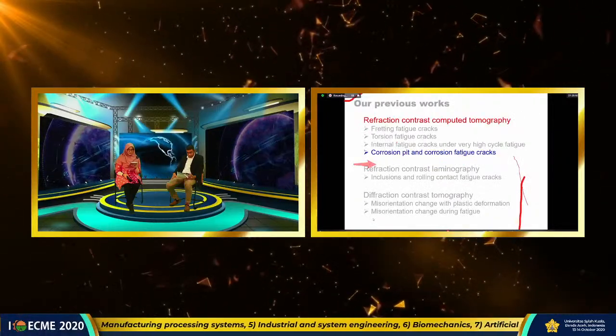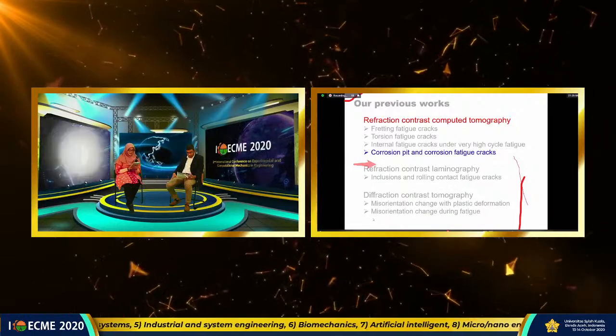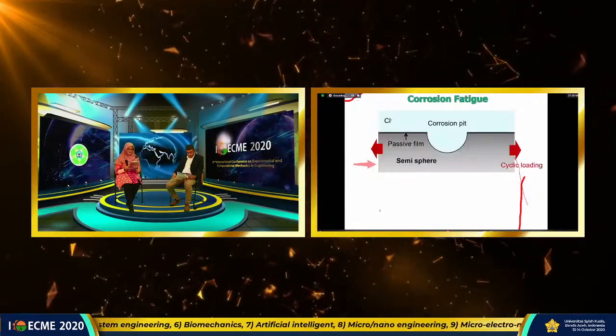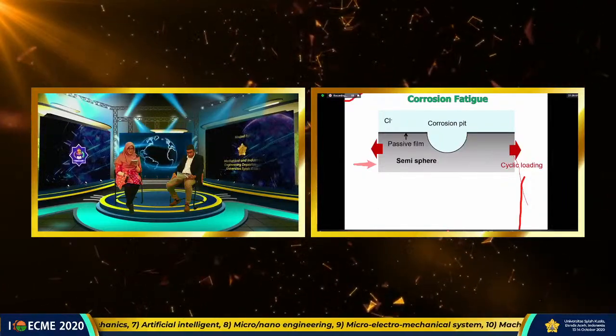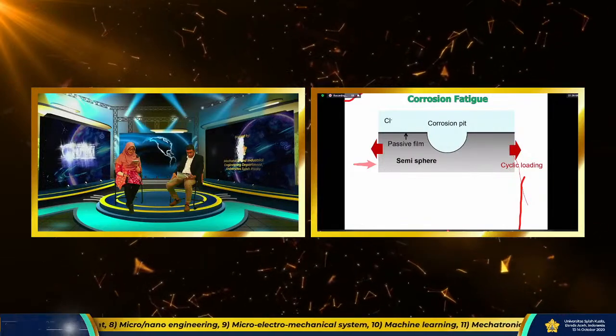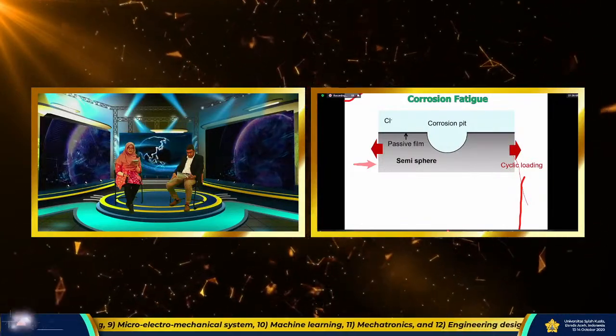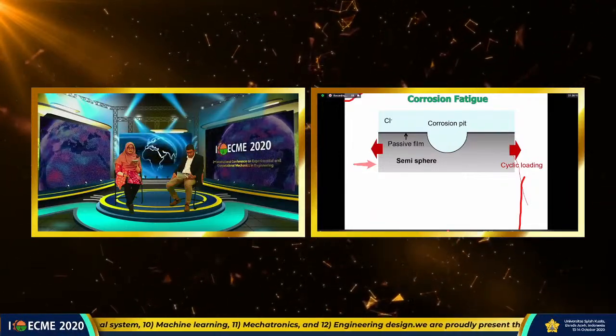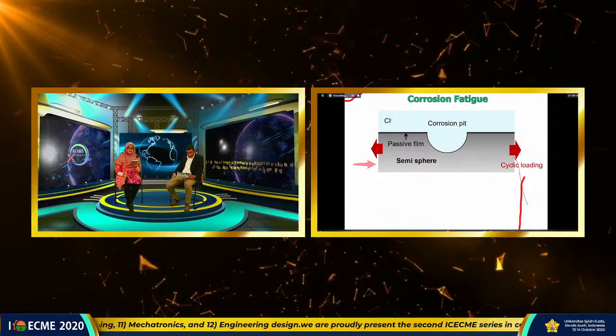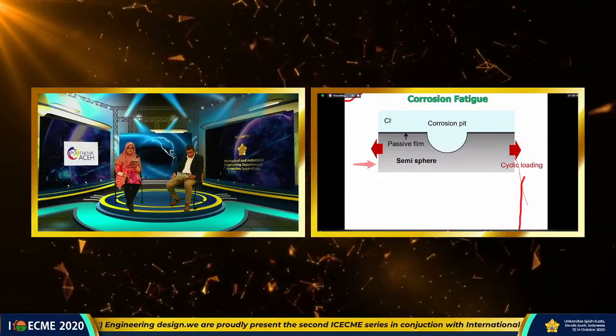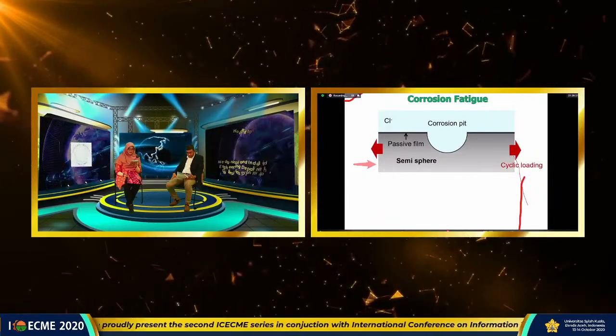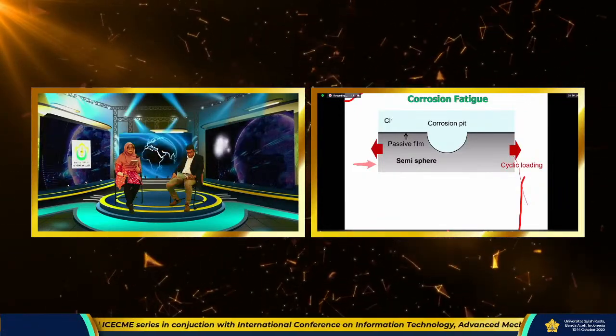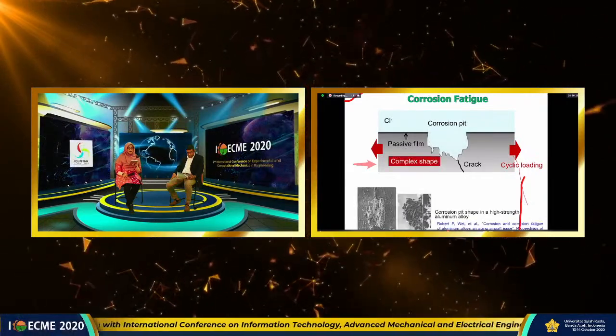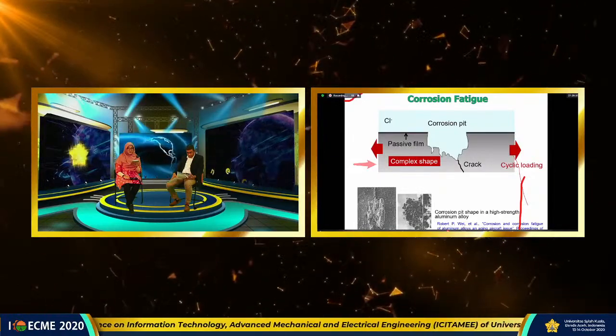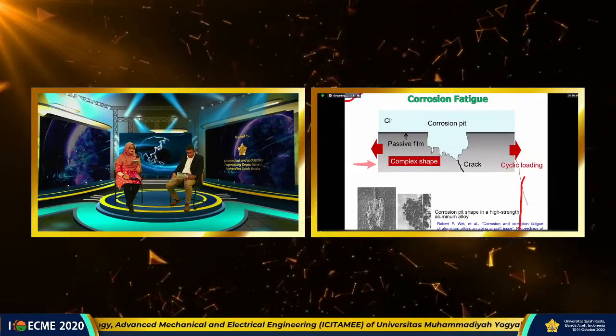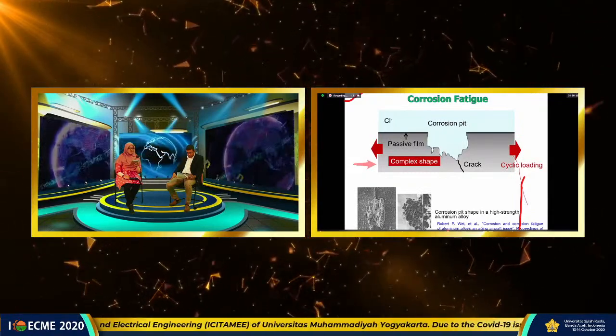Next, I'm going to talk about the corrosion pit and corrosion fatigue cracks. As you know, the degradation in strength is sometimes very severe in corrosive environment, and this is usually attributed to the generation of corrosion pits. In most cases, the shape of a corrosion pit is considered to be semi-spherical. However, the shape in aluminum alloy is very complex, like this. This one is observed by replica, and the growth behavior of this kind of corrosion pit has not been clarified yet.